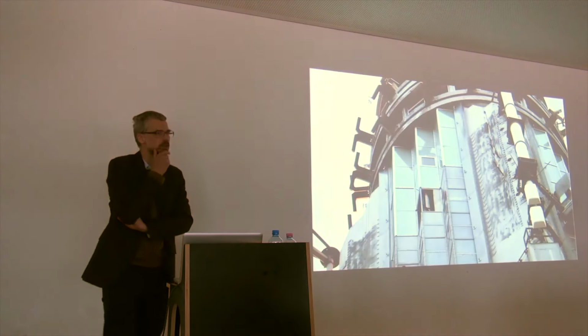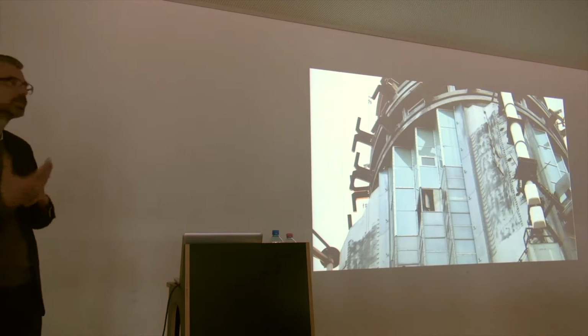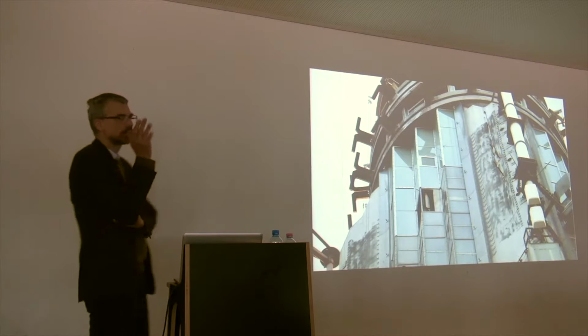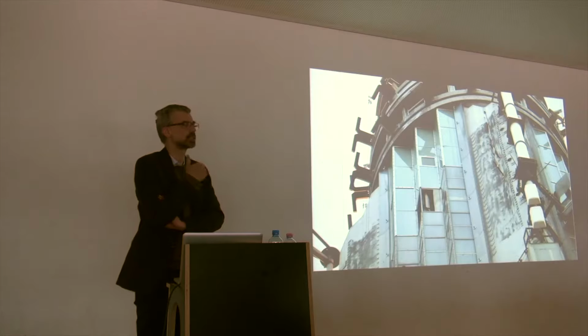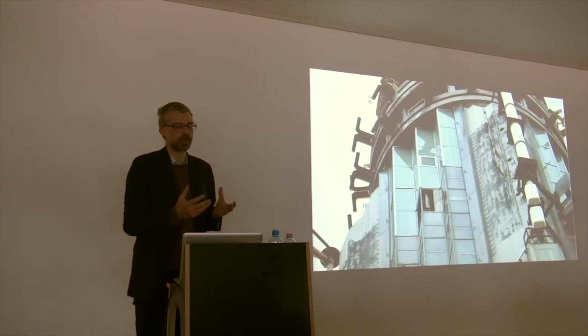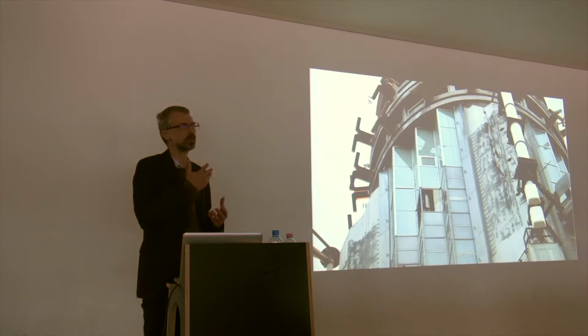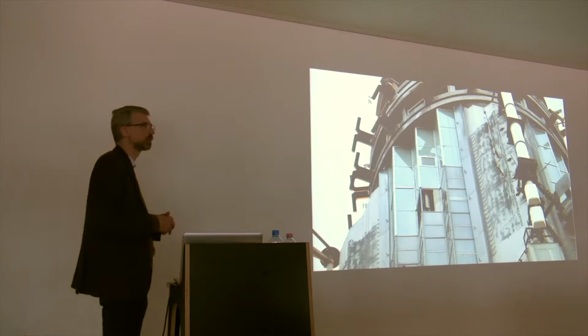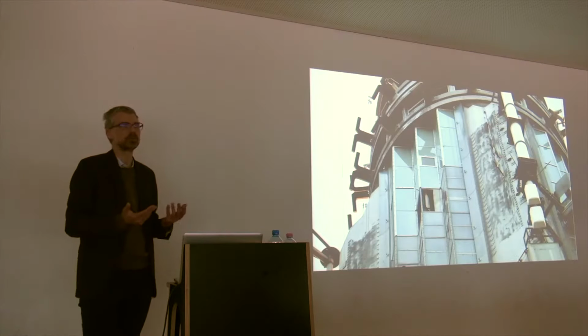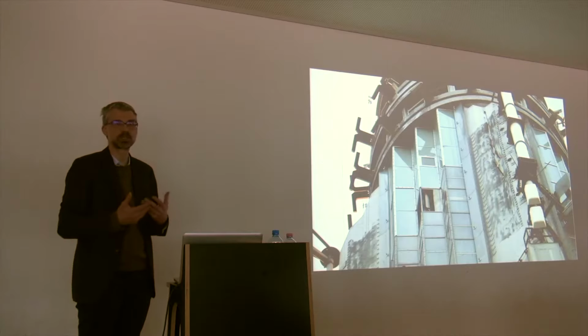So while we find solutions to develop systems that allow flexibility in size and reusing elements, talking about insulating glass units is a bigger challenge, because we have multiple layers containing a cavity which is sealed in order to decrease the amount of heat energy that is transmitting through the glass. And generally, those seals have a lifetime of 25, 30 years. And once those seals are broken, these insulating glass units would start to fog up.